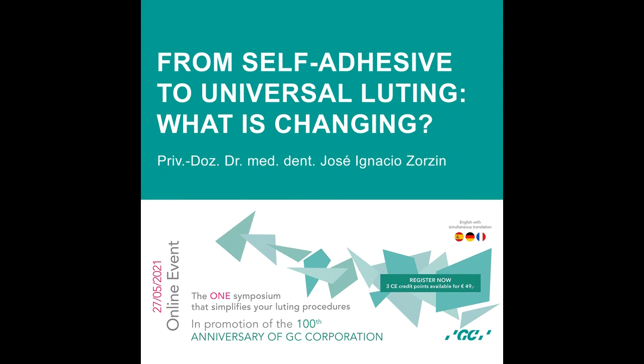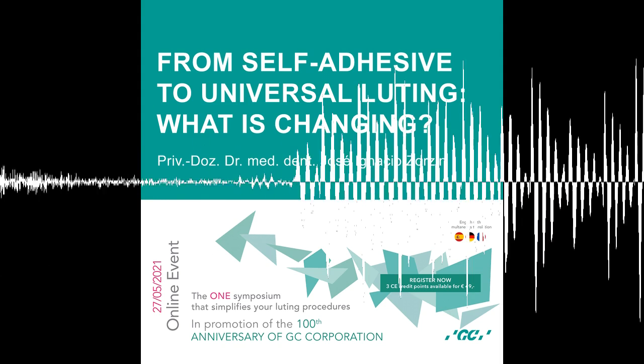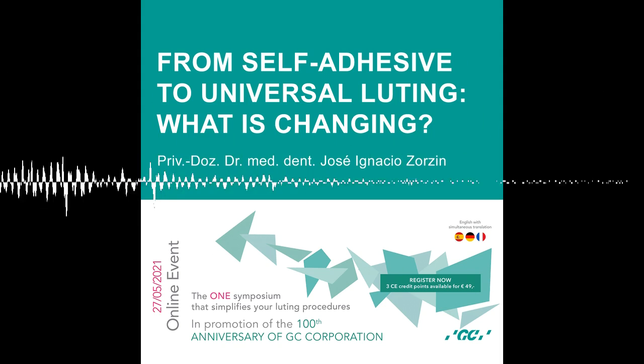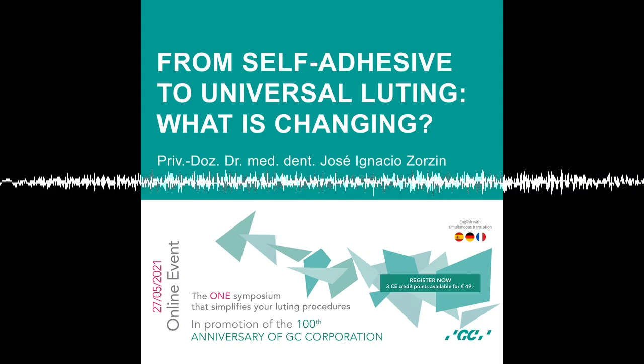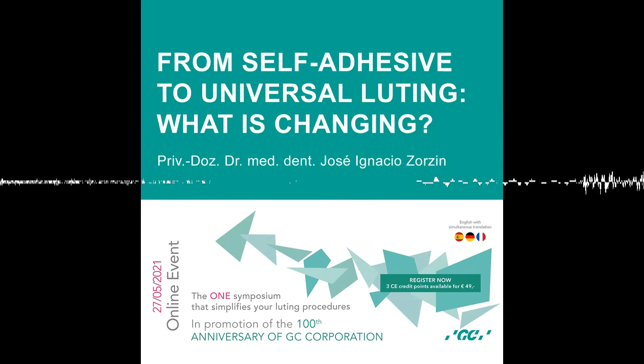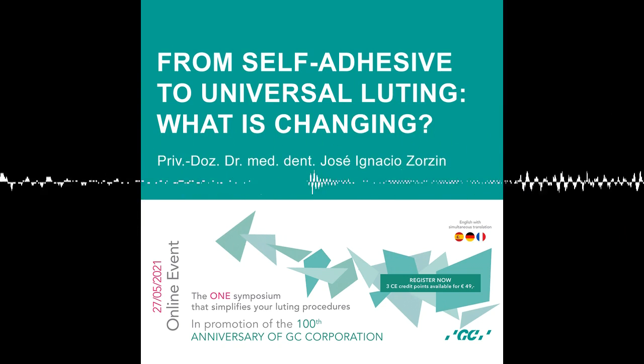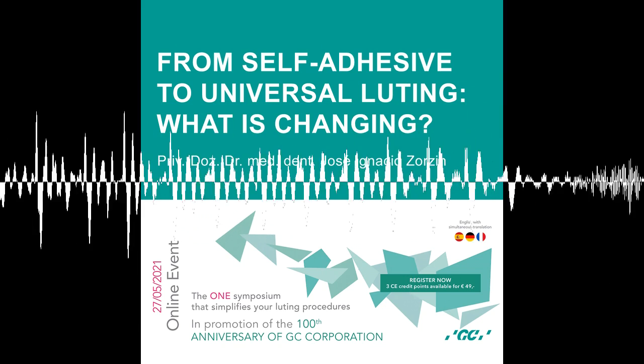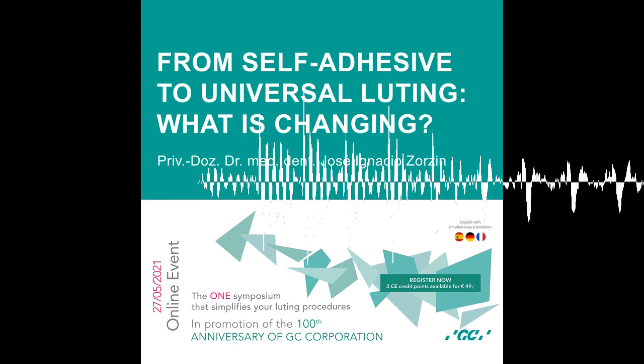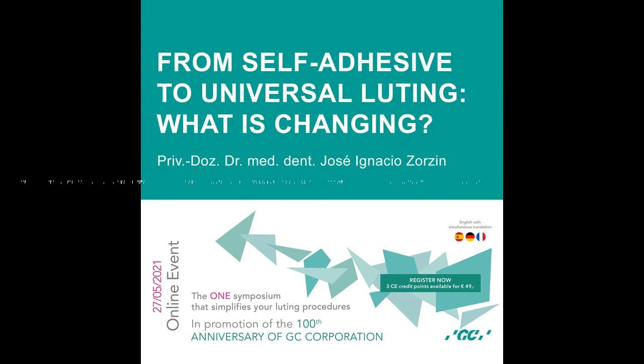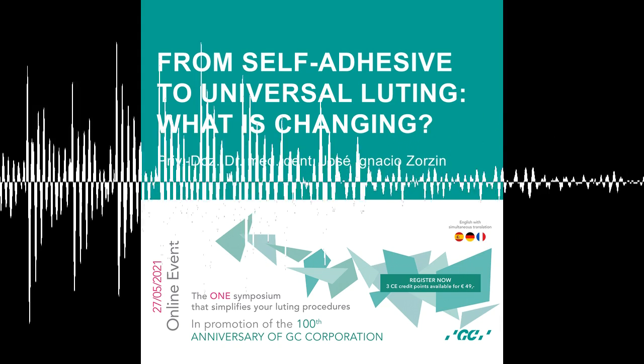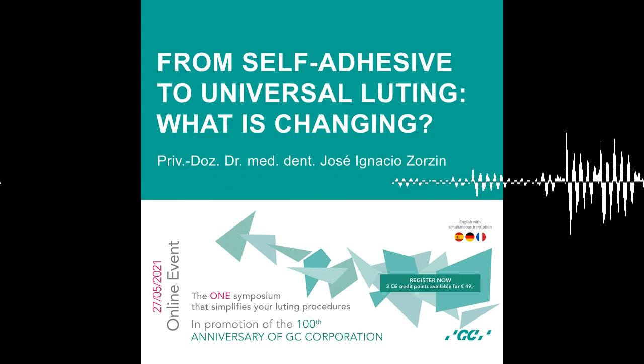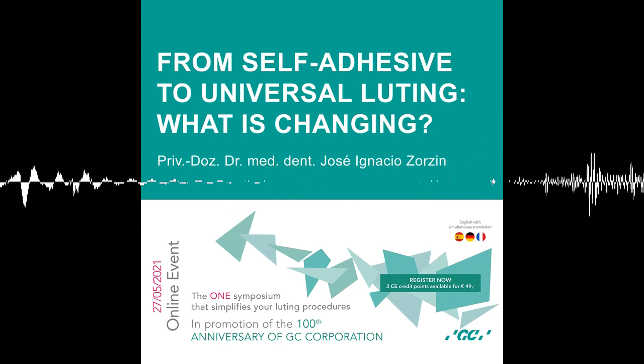So talking practically, the first step is I take a sickle scaler and first of all I try to remove all the big remnants, and afterwards air abrasion is a good possibility. You have to be careful because you can always damage the margins of your preparation. I often use aluminum powder, small, like 35 microns with low pressure, and that's a good possibility to clean.